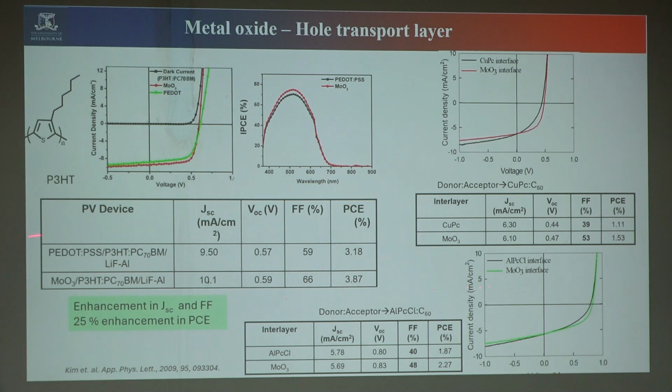At the same time, PEDOT is polyethylene dioxythiophene, a water-based hole transport layer, and PSS is sulfonated polystyrene, a sulfonic acid, which is an acidic material. For the long-term effect, this type of acidic material can start to react with the ITO, because these are all coated on top of ITO. This acid will react with the ITO and then corrode it.